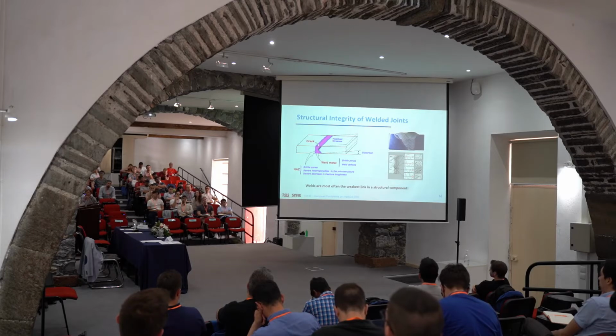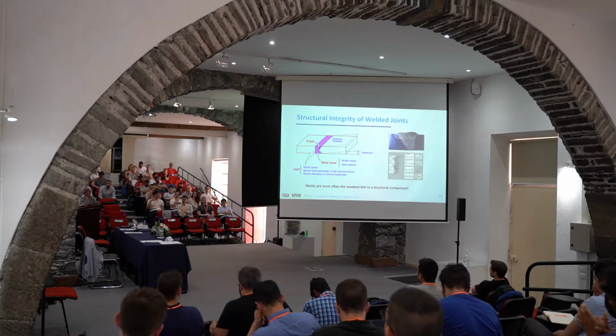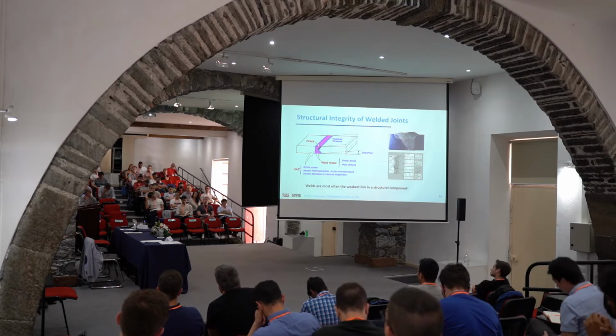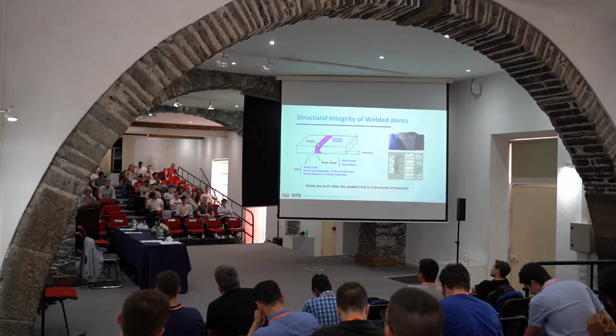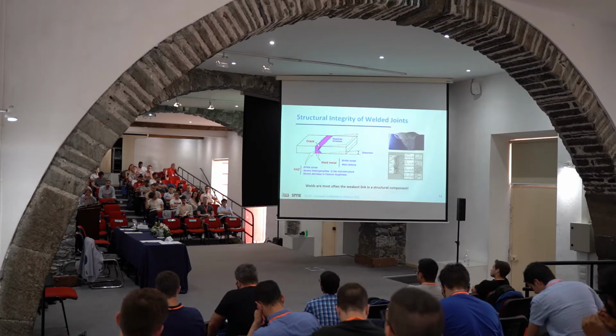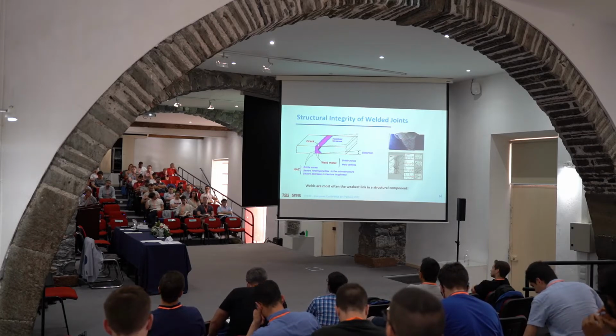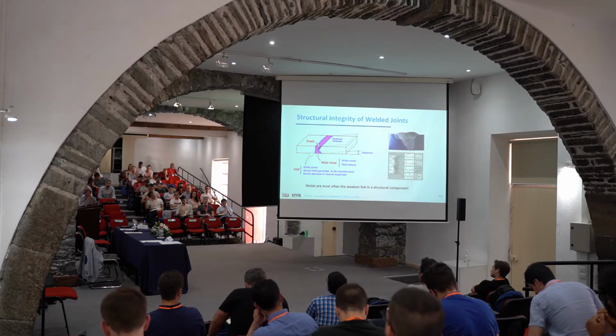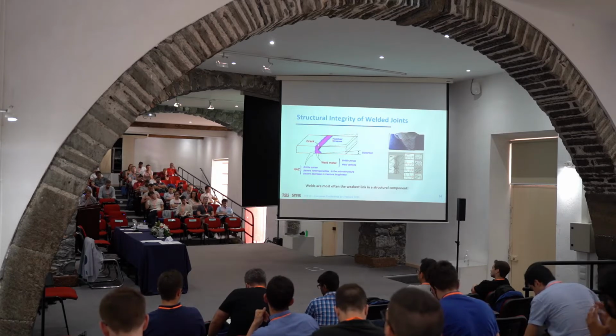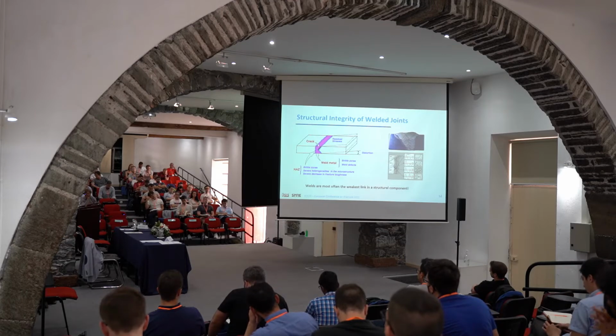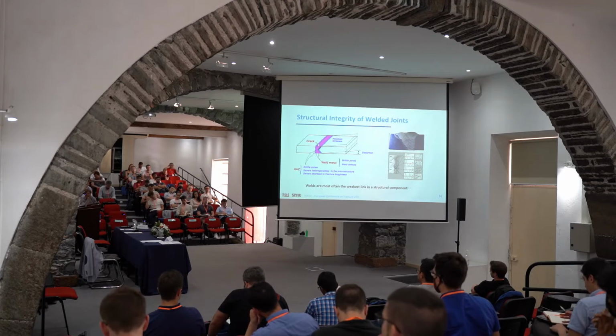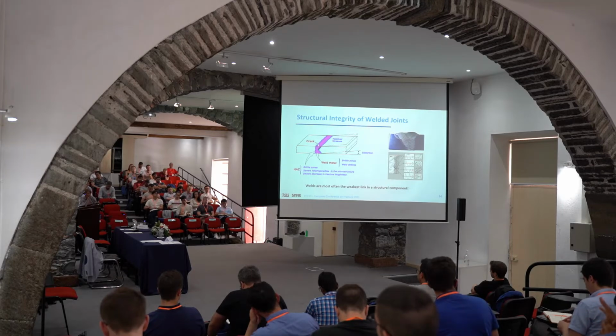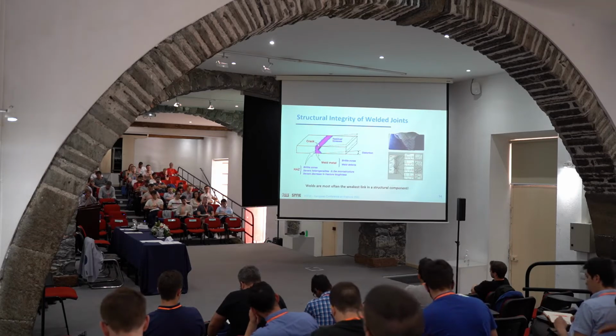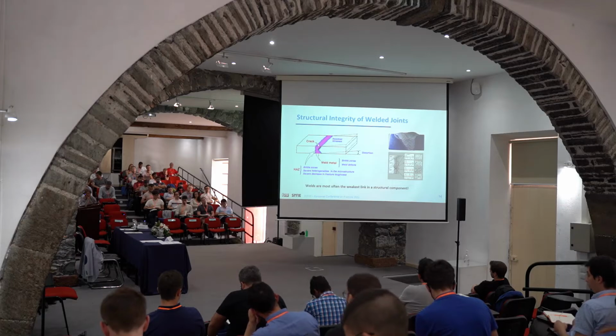This is very bad. In many steels, especially because of alloys, niobium, nickel, chromium, they all act as preferential points for the solidification of bad stuff. What we call local brittle zones. M-A islands, that's the name that they keep, M-A islands of areas rich in high carbon. Okay, so very brittle. That's one of the reasons fracture usually occurs at the weld.